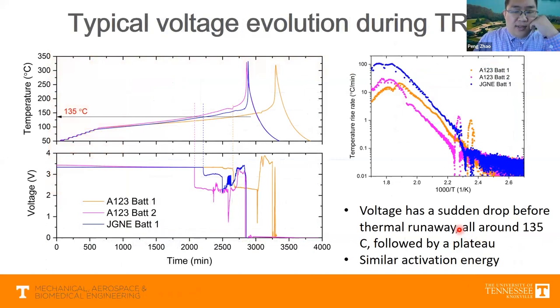But no matter what, now we trace the temperature and voltage evolution during the thermal runaway. As you can see, we still observe the cell variations. But in addition to this cell variation in thermal runaway, we also observe some good consistency. Sometime before the thermal runaway, the voltage starts to drop. And the interesting thing about this voltage drop is they all correspond to a similar temperature, 135 degrees Celsius.